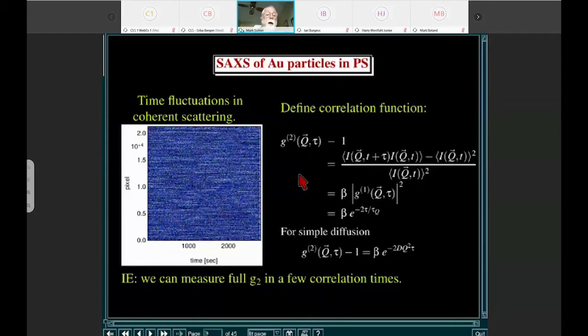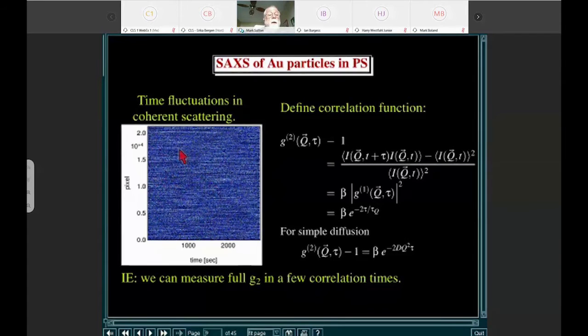Here, what I've done is I've taken a ring of isotropic scattering, so every pixel here is basically one speckle, and the y-axis is pixels or speckles. If you look at the intensity of the X-ray beam as you go around the ring at a given time, the intensity fluctuates between the bright spots, which are white, and the dark spots, where the interference pattern of the speckle is canceling the scattering. Then we measured it about every 2 seconds, I think, and what you can now see are the fluctuations in the speckles as a function of time.